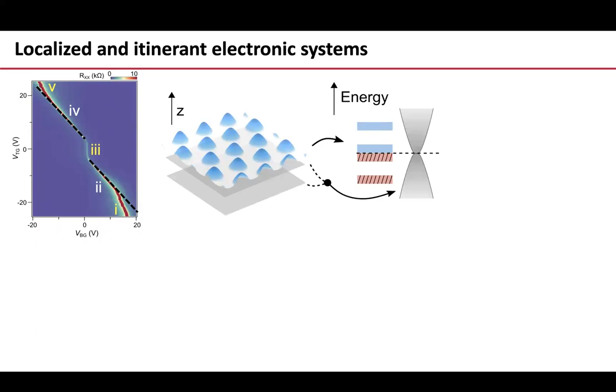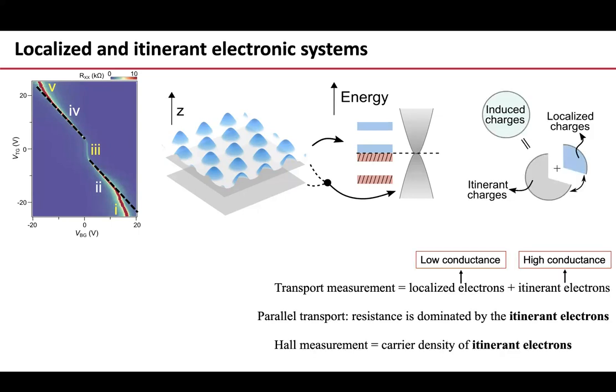This system, because of the presence of that asymmetric Moiré potential, has 2 types of carriers, okay? A localized type of carriers, which you can think of as sitting in Hubbard bands, and then an itinerant one, which you can think of as the bottom side, so to speak, of the system, which is itinerant and has a bilayer graphene like dispersion, okay? And it's highly mobile. In a transport experiment, of course, we only see the mobile carriers, the itinerant ones, because they have high conductance and they dominate the transport. The localized ones either move a little or not at all.